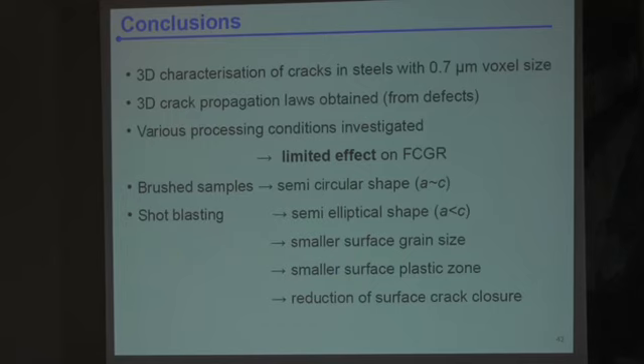Okay, so what is the conclusion of all this? The first important conclusion, even if it's not so obvious, is that it is indeed possible to watch the cracks growing in 3D in a material like steel, which is a strongly attenuated material. Usually we work with aluminum, titanium in some cases, but it's harder. But still now it's feasible, and that was also a good result, even if for the case we studied, we had no large effect of the process on the crack shapes and the crack forms, except on the crack aspect ratio, which we explained by a reduction of the surface crack closure due to this microstructural gradient induced by the shot blasting at the surface.